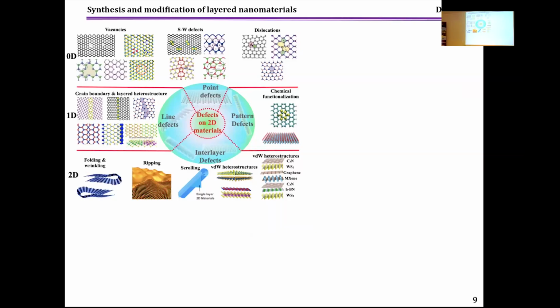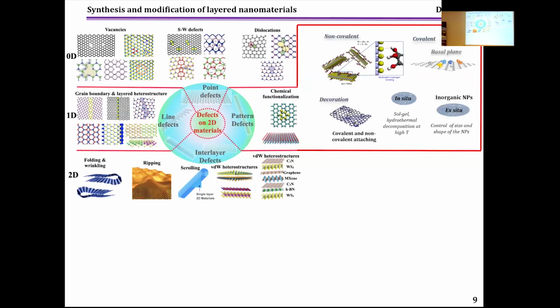So among the modification strategies to improve the properties, we have different defect creation. The first one is the creation of point defects. It includes vacancies and dislocations, grain boundaries, and chemical functionalization, which is one of the most widely reported. In the case of chemical functionalization, we can prepare materials which are modified non-covalently with organic molecules, or also with other inorganic systems. We can make covalent changes in the basal plane, and also we can induce decoration with inorganic systems. They can be oxides or metals by themselves. We can make in situ and ex situ modifications.